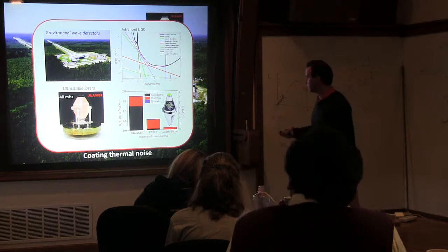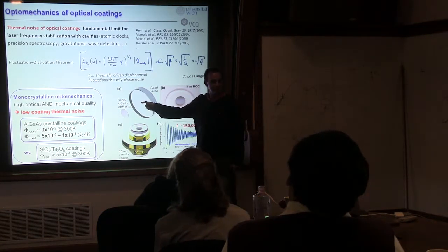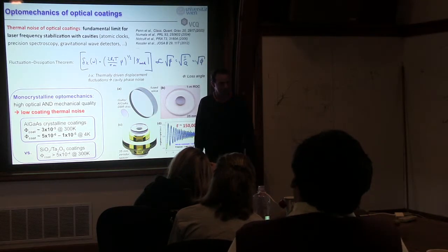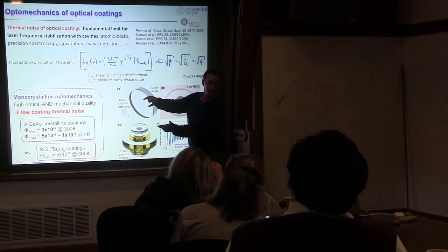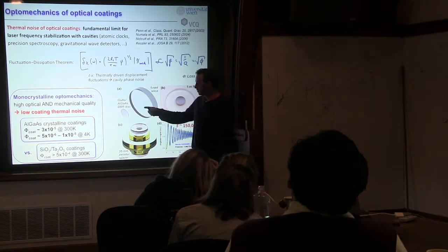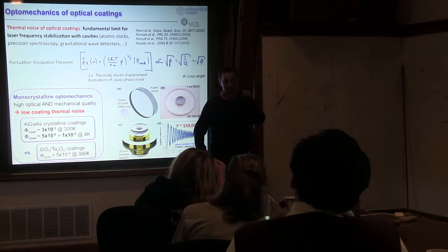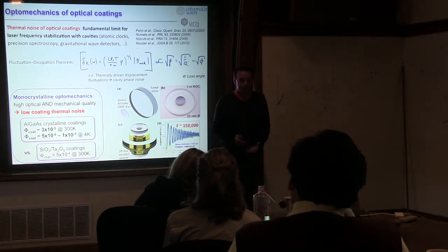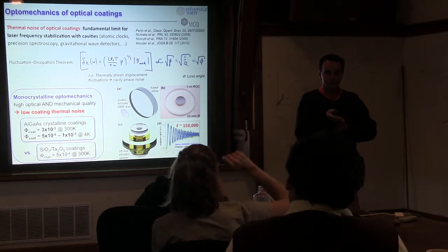And then the next thing was they thought, if you bond that here on the interface, we will have mechanical losses at the interface, and that's going to kill it. So this was the second argument after the absorption, and the fact that you cannot transfer it. And that also turned out to be not true. I guess that's because this is really a nice chemical bond. It's a covalent bond that you create. There is no interface really.